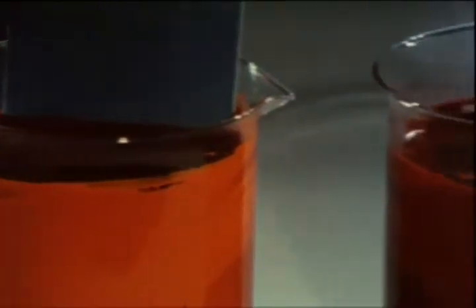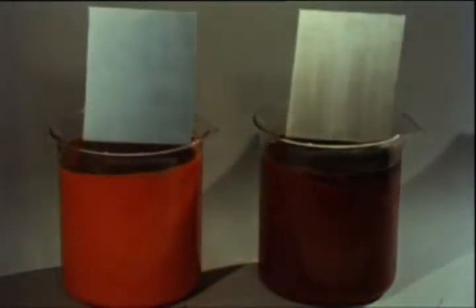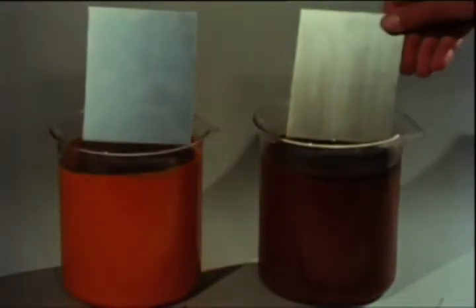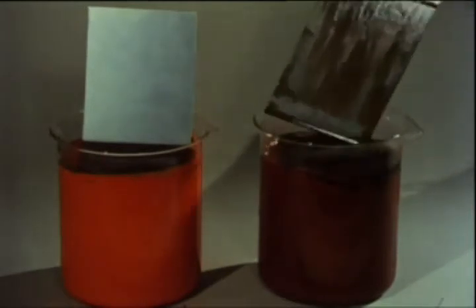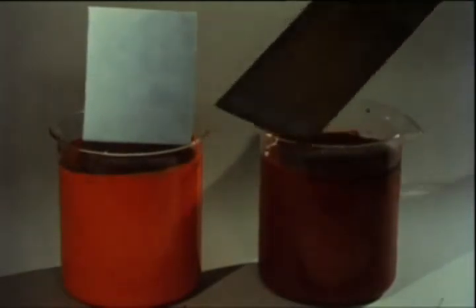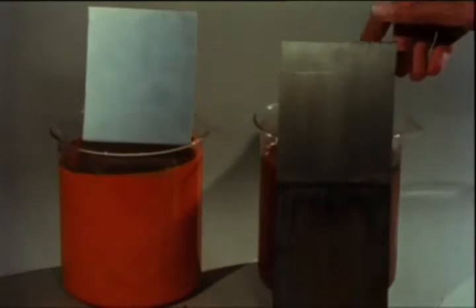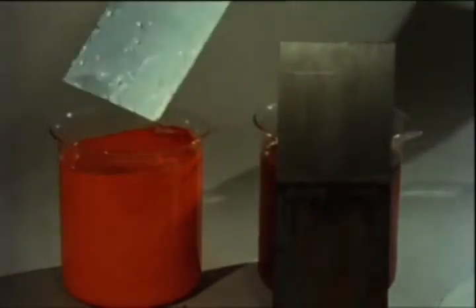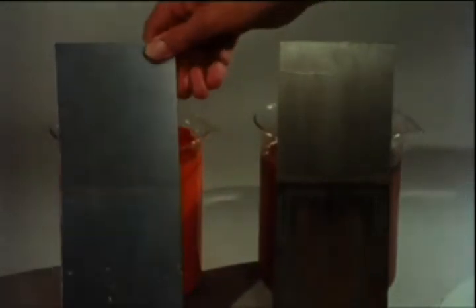A clean steel plate is put in each beaker. After a week, the plate in the iron oxide and linseed oil has rusted. But the red lead and linseed oil has formed an active compound which has leached into the water to prevent corrosion. Corrosion has been controlled by chemical action.